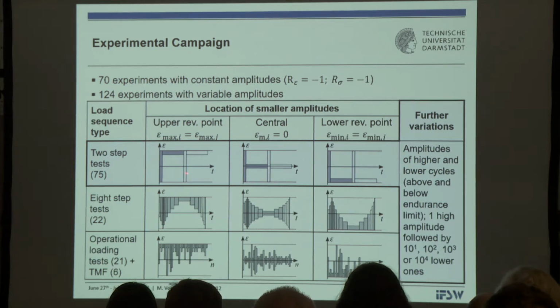And finally, we performed a lot of two-step tests consisting only of a large cycle, large amplitudes, followed by a number of small amplitudes, either at the upper reversal point, the lower, or somewhere in the middle. And we varied the amplitudes of the large and small cycles, especially the small cycle amplitudes were chosen to be either just above the endurance limit or just below the endurance limit. And the number of these cycles was also varied between 10 and 10,000. So finally, this campaign had 70 experiments with constant amplitude loading and 124 experiments under variable amplitude loading.